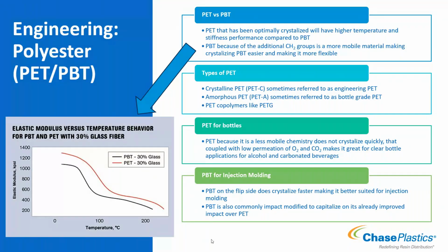There's also copolymers. If we take PET and copolymerize it with glycol, you get a material like PETG. If you've seen those materials floating around, that's a variant of PET, copolymerized. So for PET bottles, again, we stop it from being able to crystallize, and it doesn't want to crystallize quickly either. We make effectively an amorphous or bottle grade version of PET.